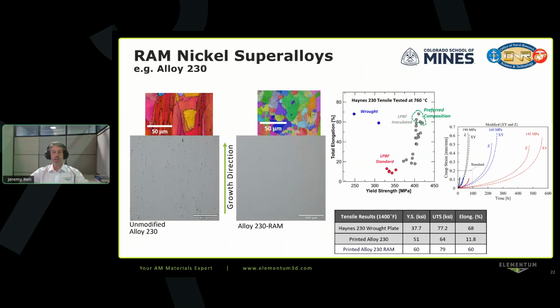So this RAM process, it's versatile. It's applicable to many different alloy systems, not just aluminums. Here's an example in nickel superalloys. This is looking at an alloy 230, like a Haynes alloy 230 type system, which is known to be weldable by traditional processing. But when you get to the very high thermal gradients of laser powder bed fusion additive manufacturing, you do get these micro cracks throughout the alloy that form. So you get very small cracking along the grain boundaries from solidification-based cracking and a very columnar microstructure that forms.